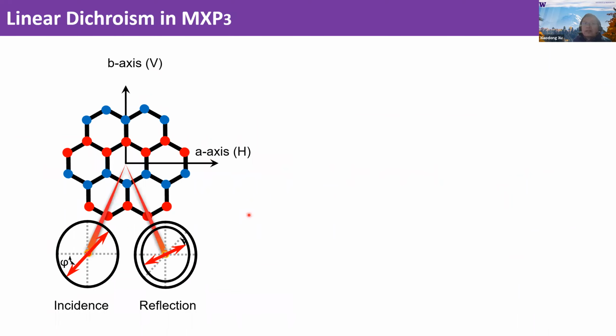So now what I showed you is that we have the zigzag antiferromagnetic order, and it introduces a strong optical anisotropy. Then this optical anisotropy can also be measured through linear dichroism. So in the linear dichroism measurements, what we do is send in linear polarized light, and then we measure the optical reflectivities.